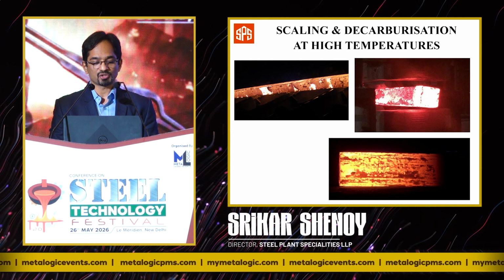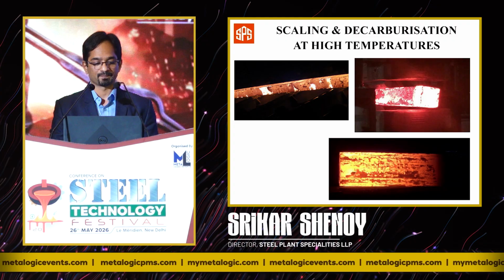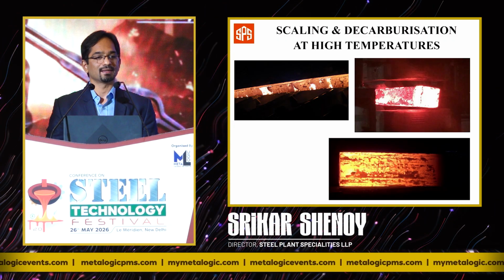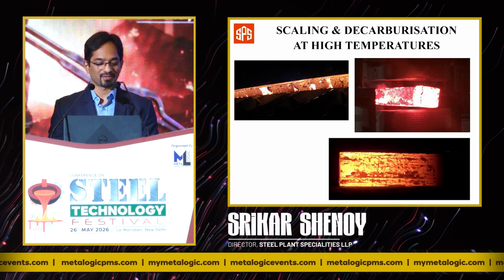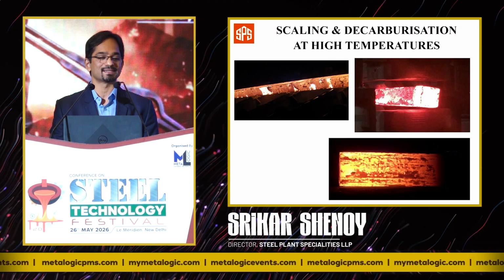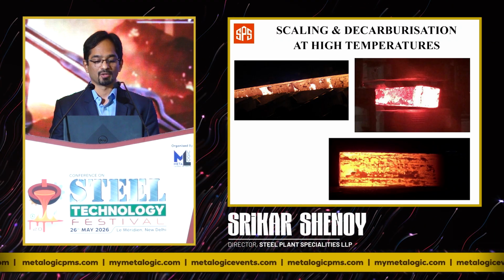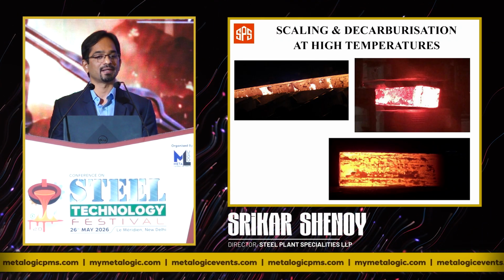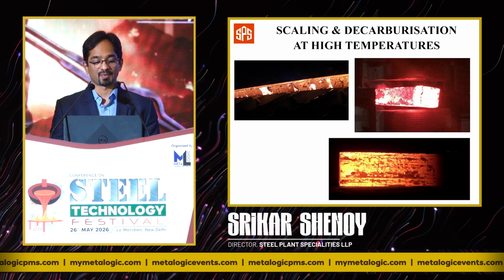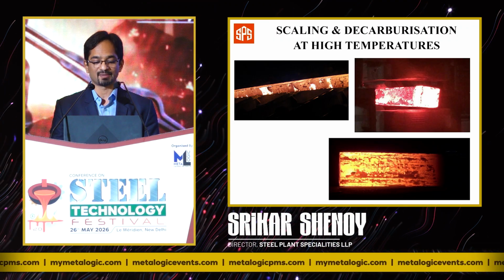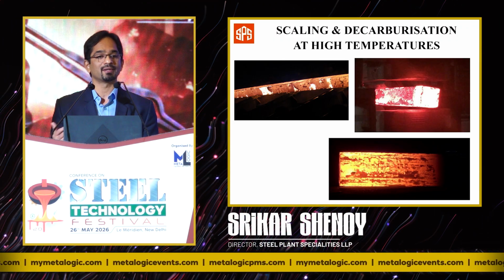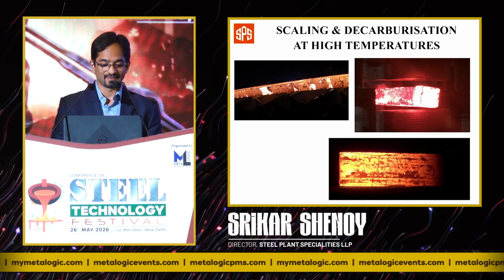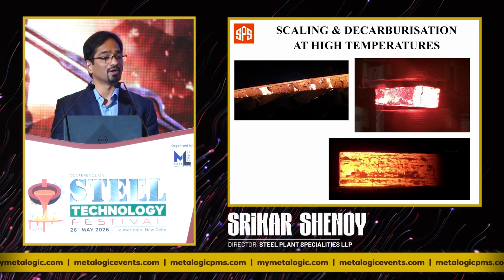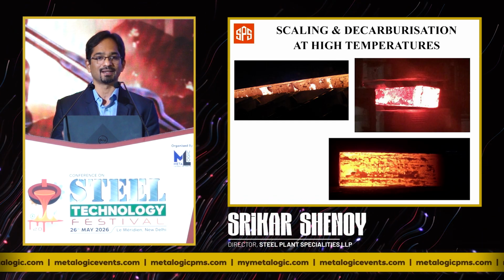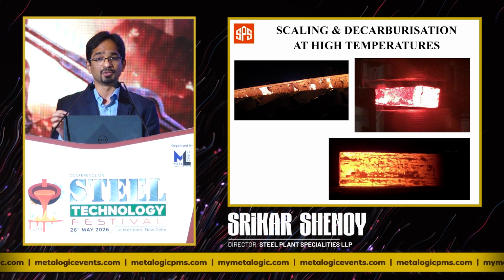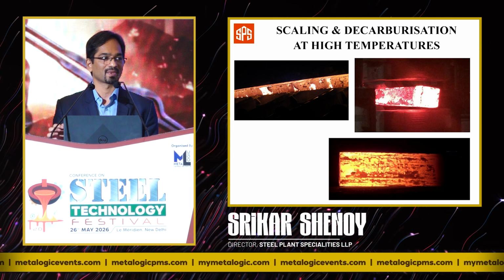At every stage of heating steel, scaling is inevitable. What you're seeing on the screen on the top left is a billet that is heated and there is scale on it. Top right is an ingot heated at 1250 degrees Celsius. Prior to open die forging, you can see the scale present on it. Even if you use modern technologies like induction heating, this is an induction heated billet. However, depending on the grade of steel and metallurgical parameters, you do experience scaling.